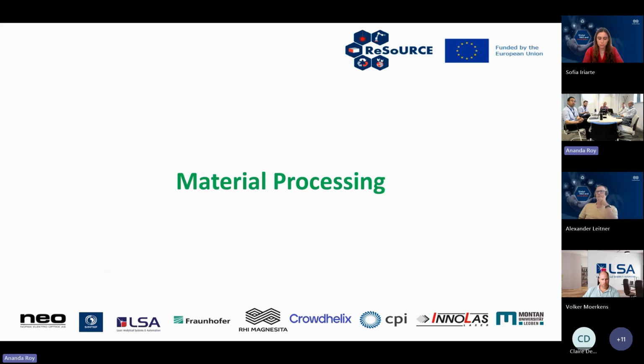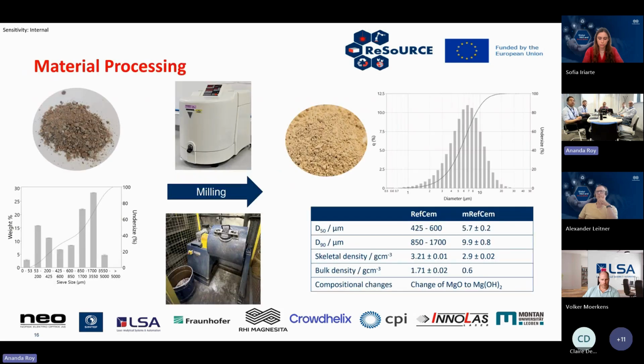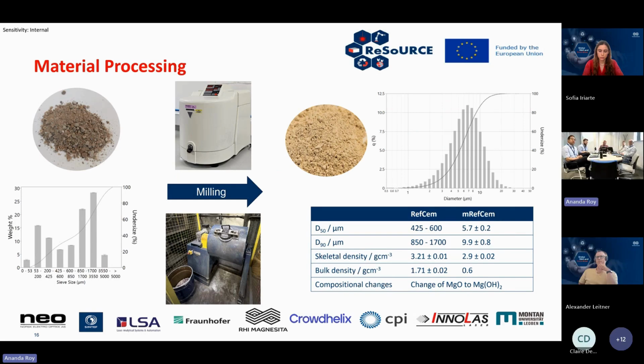So the materials were of a 0 to 5 millimeter size class, and we realized that for certain applications we might need to do some processing and change the size class of these materials to an appropriate size for the specific applications. So a lot of the applications we've looked at are using these materials in polymer composites, where we need a D50 that's below 10 microns.